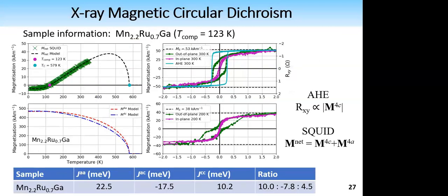So on this slide is a summary of the magnetic properties of the sample studied, which was manganese 2.2, ruthenium 0.7, gallium, which has a compensation temperature at 123 Kelvin. So from the zero field temperature scan, which was performed in SQUID, I was able to take it and again do the mean field theory fitting to predict what the behavior of the manganese 4A and the 4C sublattices. On the right, I'm showing the SQUID loops of the net moment, and I'm also showing for the 300 Kelvin case, the anomalous Hall effect loop, and we can see again coercivities are matching.